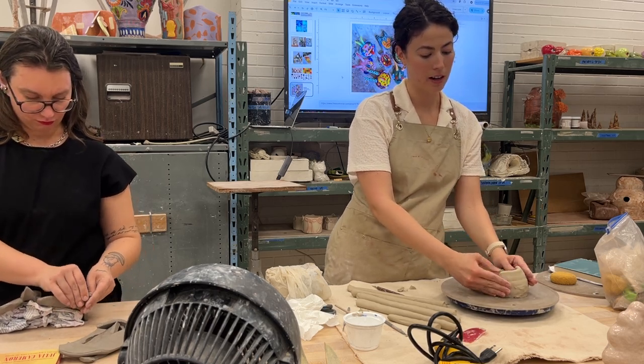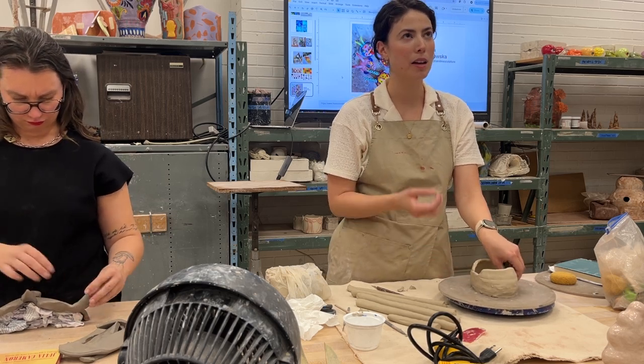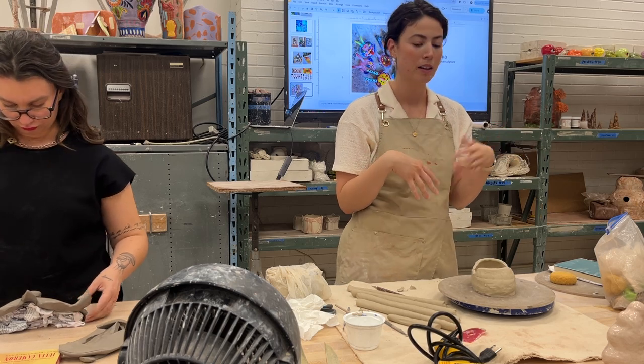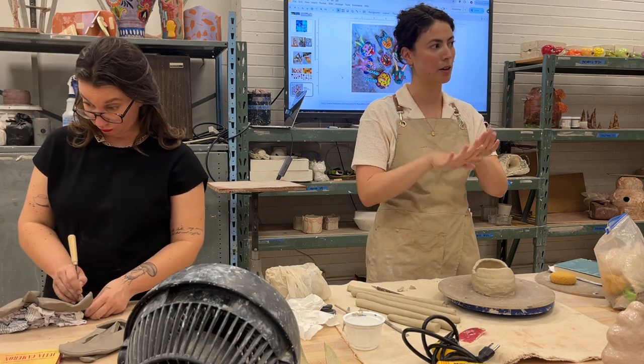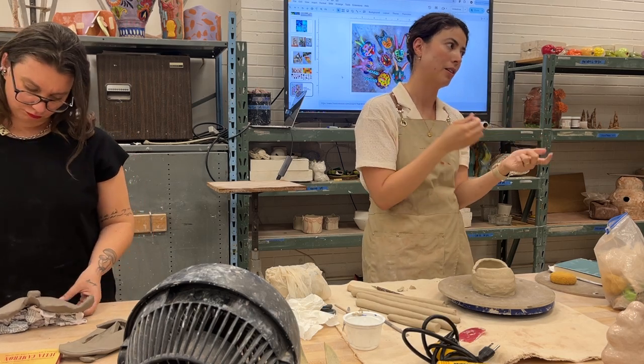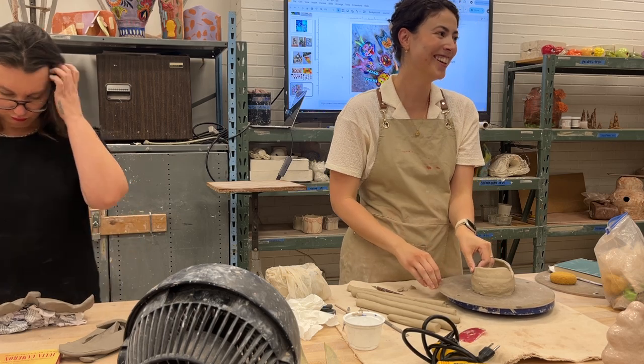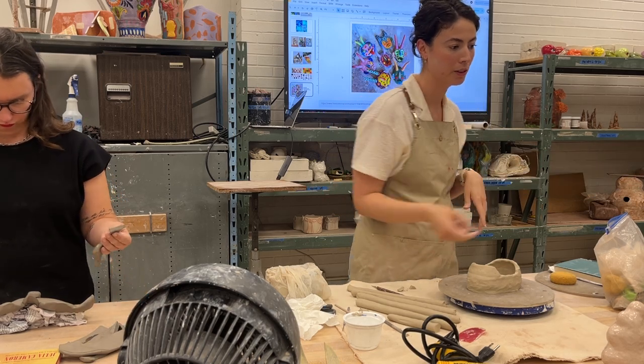This is B-Mix. I also really like Cinco Rojo, and Buffalo Wallow. Buffalo Wallow, at least the bags that I have gotten, have tended to be a bit softer, which is great for a lot of things, but for something where I'm wanting a lot of these undulations, it's kind of tricky to work with, unless you have something like a heat gun, which also helps. I'll probably demonstrate that in a moment, where as I'm getting ready for a big transition, you want to make sure the clay is stiff enough to handle that. And additionally, there's the moisture content as well as the thickness of the clay. So yes, I'll talk about that as I go along. But to answer your question, Cinco Rojo and Phoenix are the two main ones that I use. And then Buffalo Wallow, this guy's Buffalo Wallow.